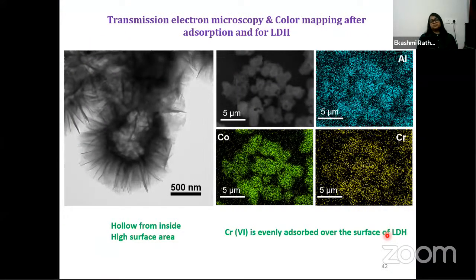Another interesting part was that I visualized my powder samples at the nanometer scale with the help of transmission electron microscopy, and we found that these layers are hollow on the inside. This hollow nature gives rise to high surface area, and if there is high surface area, then there is more probability of these heavy metal ions getting captured. And from the colored mapping images, we figured out that chromium is evenly adsorbed over the surface of the LDH.